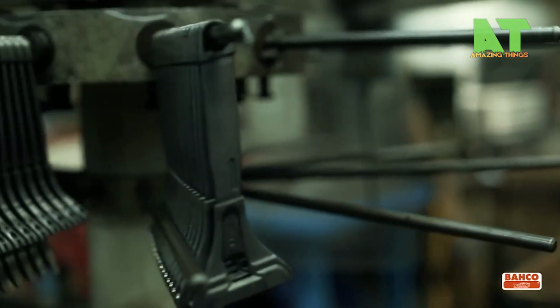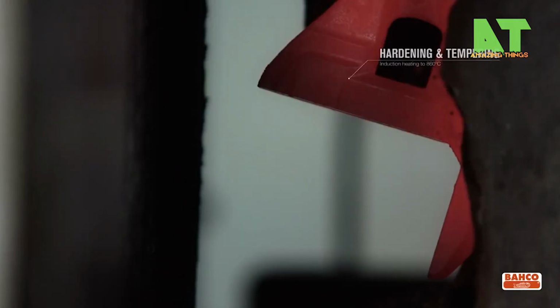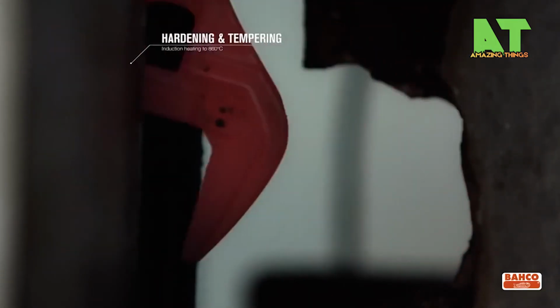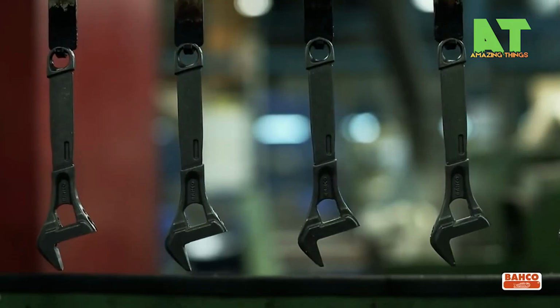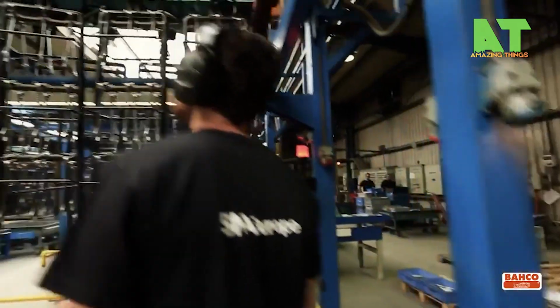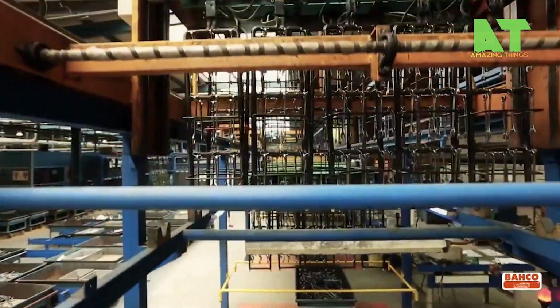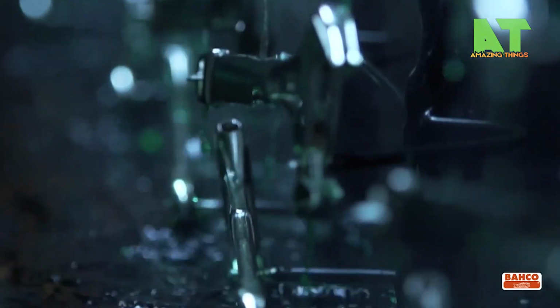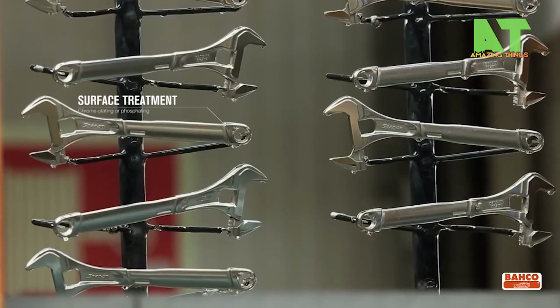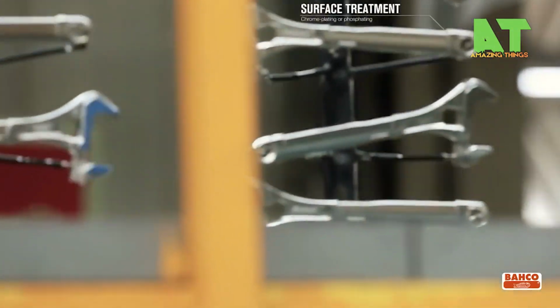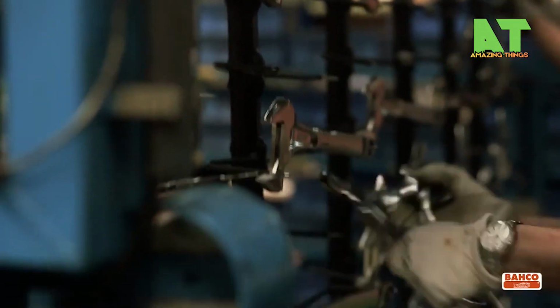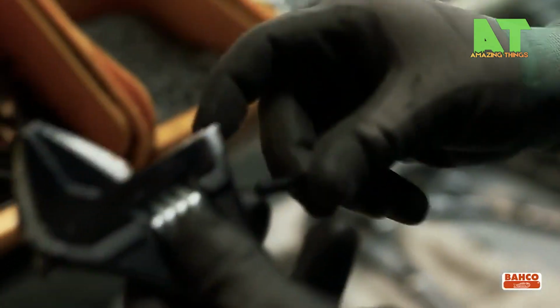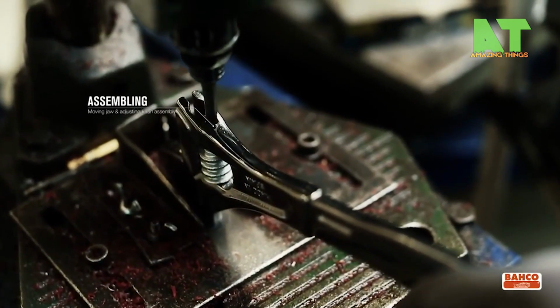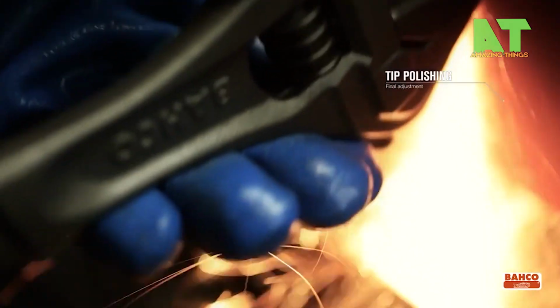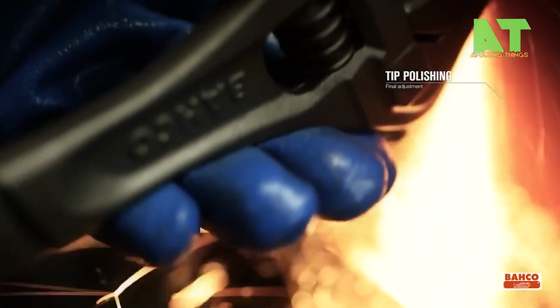the adjustment slot are precision machined to tolerances measured in hundredths of a millimeter. This tight precision is exactly what gives a Bahco wrench that smooth, non-slip grip on a fastener. The worm gear, that little knurled wheel you turn with your thumb, is manufactured separately and pressed in with a precision fit. Then the entire assembly goes through heat treatment and surface hardening to extend the life of those critical jaw surfaces. Finally, a dip in a chrome plating bath gives the wrench its signature polished look, while adding a layer of corrosion resistance. Each unit is inspected, stamped with its size specification, and packaged.